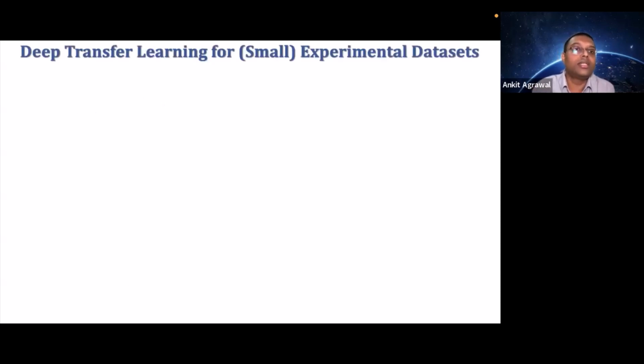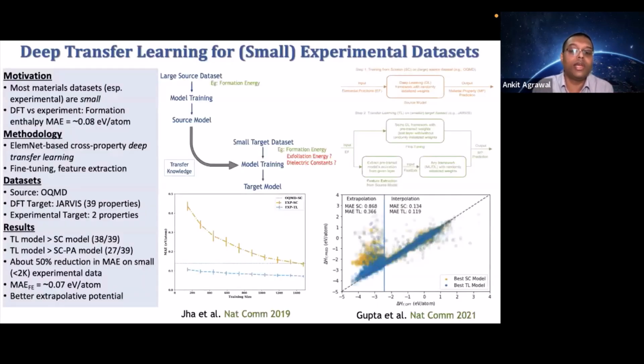So there is this idea of deep transfer learning that we have applied over the years for small, especially experimental, data sets. As we know, most data sets are small, and we are using DFT to train the models till now, right? The OQMD and JARVIS and all. And DFT is not ground truth. So there is some error with respect to experiment, which is about 0.08 electron volts per atom in the data sets that we analyzed in this work.